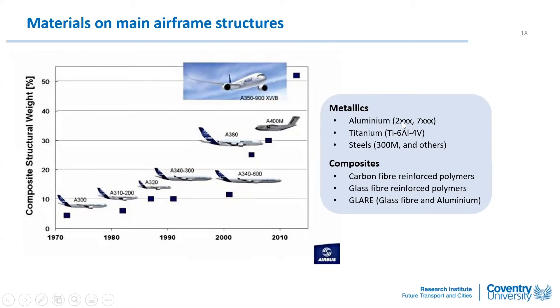The 2000-series aluminium alloys are excellent for fatigue resistance and are used for wings and fuselage shells. The 7000-series are used for spars, stringers, and ribs due to high strength and stiffness. Titanium alloys are used for fittings and joints, and their usage will increase as composites are introduced because aluminium has a galvanic corrosion problem with carbon fiber. Steel is very heavy and avoided where possible, but 300M steel is used on landing gear.